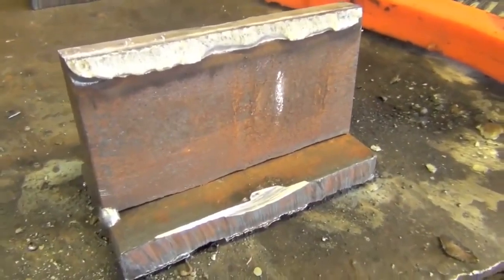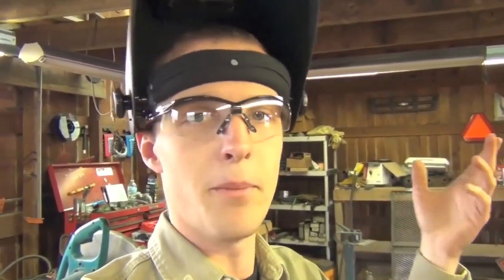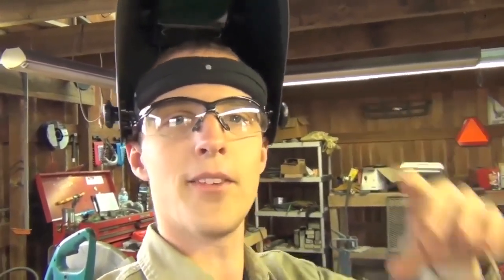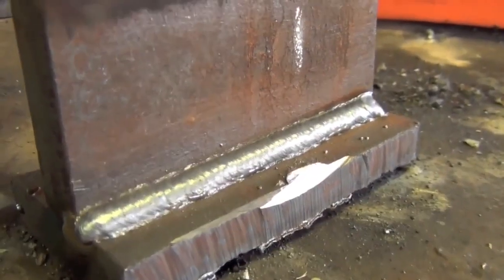Now, in order to not deeply penetrate into our base metal, we're going to be using this 3/8 plate. Basically, what's going to happen is this is not enough heat to melt the base metal. This is only enough heat to melt our filler metal, our MIG wire. So that's the only thing that's going to melt, and instead of going into the base metal and tying into it like it should, it's just going to pile up on top of itself because there's really nowhere for it to go, at least not running this low amperage. So let's see what that looks like. Wow, look at that cold lap.